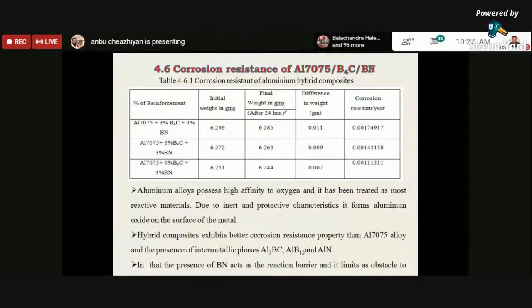In addition, the inclusion of secondary reinforcement acts as a heterogeneous nucleation site, and it acts as a barrier to grain growth, and hence the grain size of the composite has been reduced. So that is also an important factor which is considered in the increase of corrosion resistance of aluminum hybrid composites.